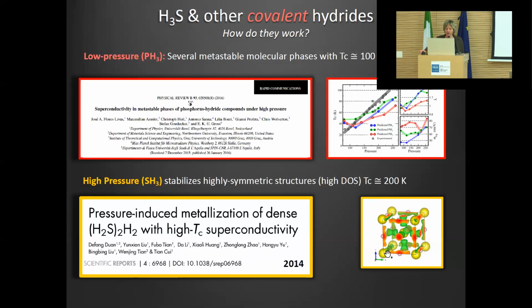I show here the crystal structure. You see here these yellow balls are sulfur, these small balls are hydrogen, and what you see is a highly symmetric lattice where each sulfur is bound to 6 hydrogen, and you see this is basically the charge, and you see that there is a localization of charge between hydrogen and sulfur, which says that basically in this case we have a covalent bond between sulfur and hydrogen. This is something that should never exist at ambient pressure, but we are not working at ambient pressure. We are working in the megabar range where forbidden chemistry takes place.